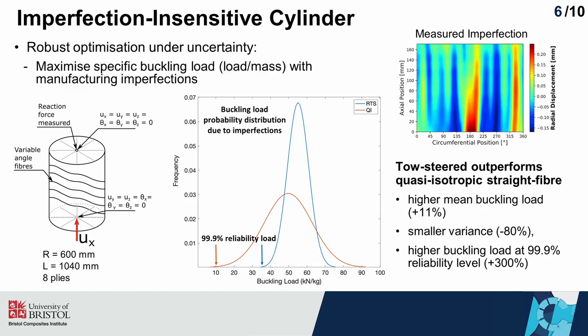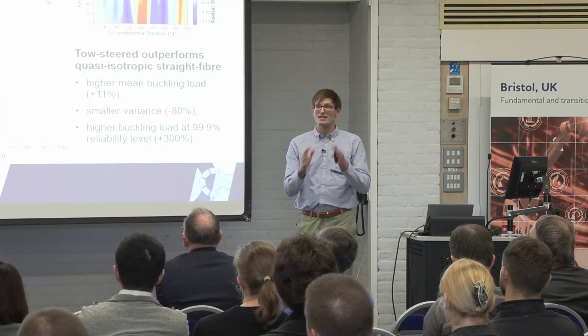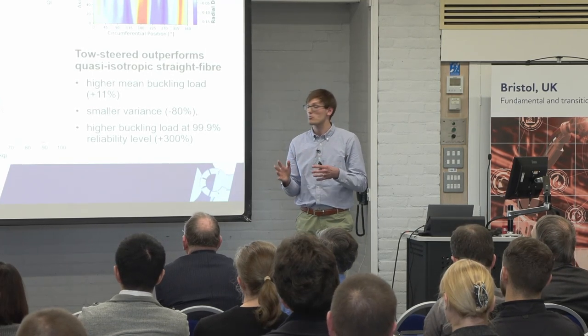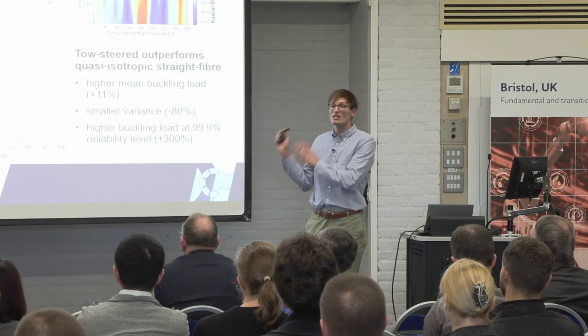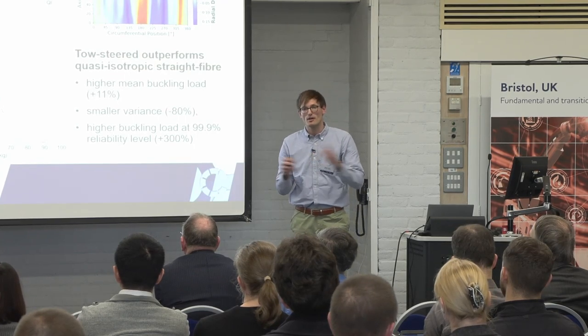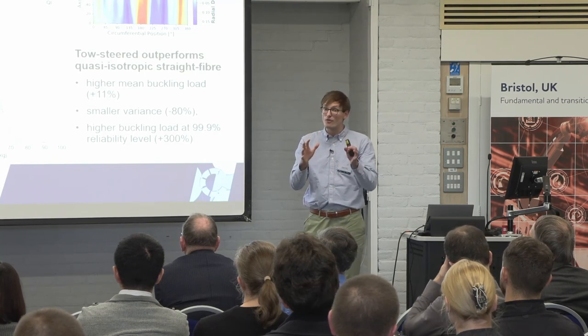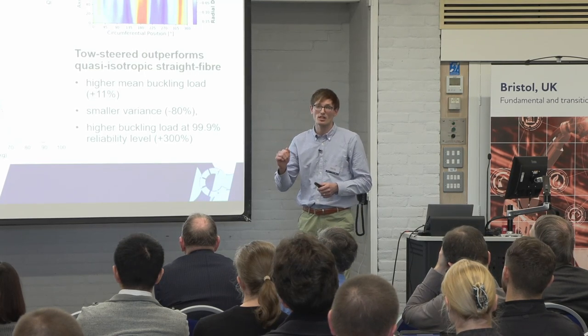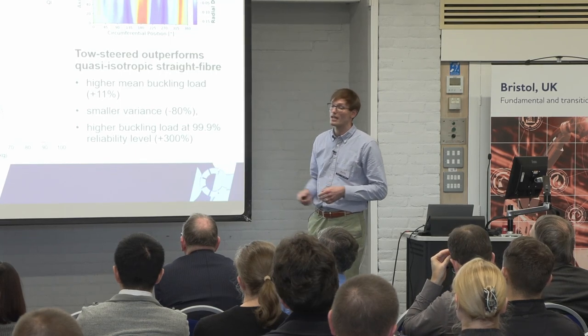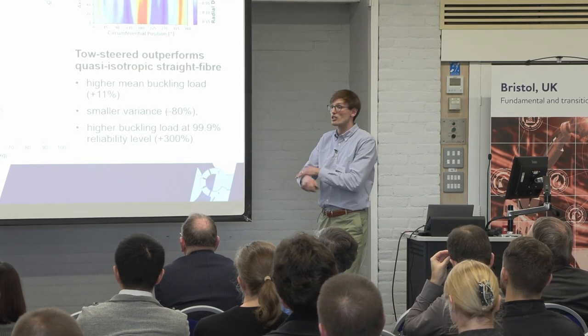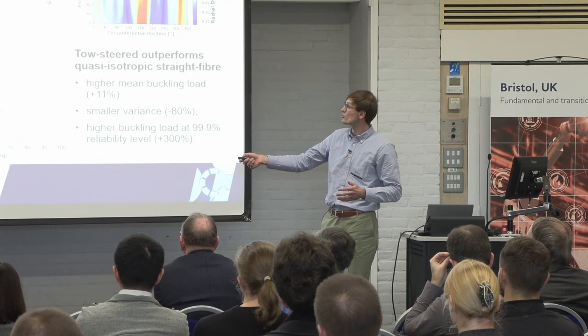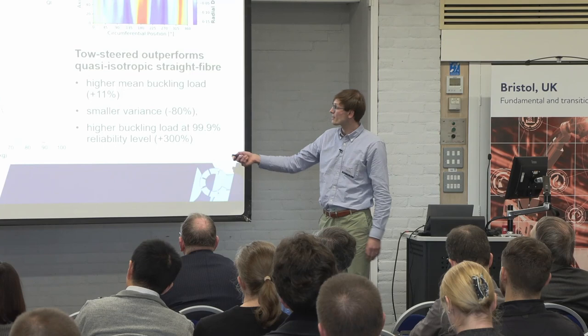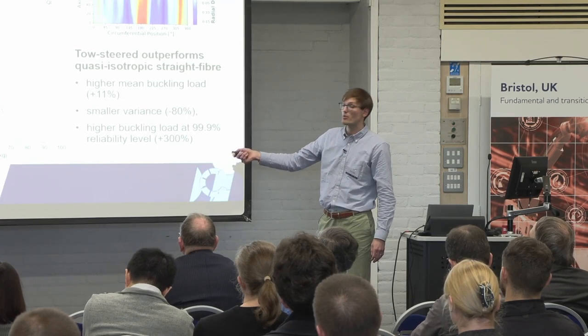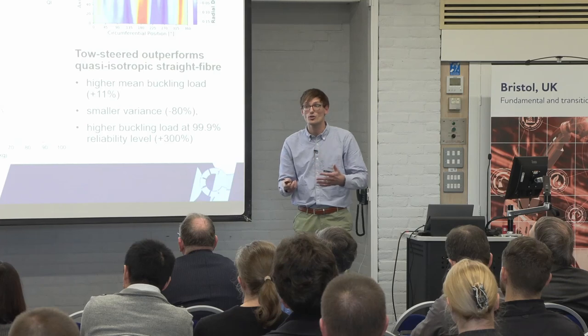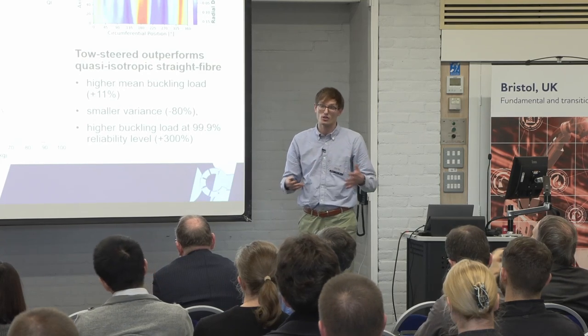And here you see two different distributions. The first one in this red-orange color was our benchmark, the baseline design, which was a straight fiber, 8-ply quasi-isotropic design. The reason why it's quasi-isotropic is because it's a well-known literature result that if you have a perfect cylinder, the highest possible buckling load is for a quasi-isotropic. And so that's why that cylinder was chosen. And then we essentially went away and we optimized these fiber distributions to try to maximize a worst case scenario. So the 99.9% reliability load, which is often used by the European Space Agency to design their space structures.